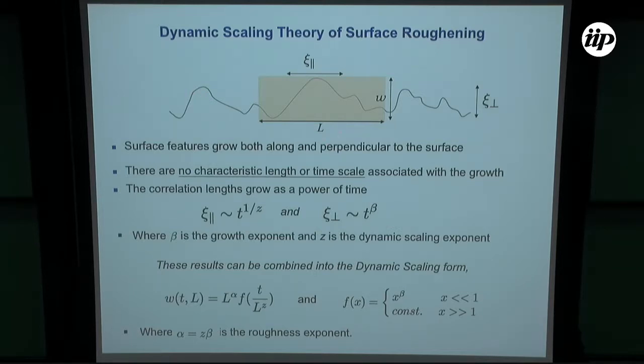And because after some time the surface evolves according to what is your length scale of observation, these two ideas can be combined into a dynamic scaling form, in a sense that the width grows with this exponent alpha, which is z times beta, times some universal scaling function that has a very specific property. This universal function has to grow at x to the beta for a small x, and at long times it reaches a constant because the system evolves into length L.